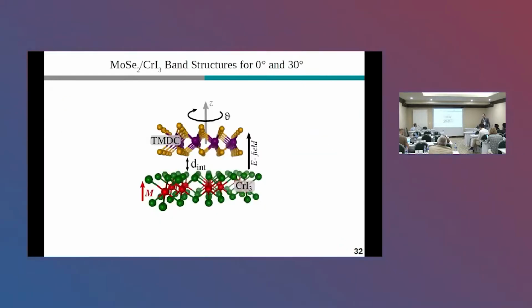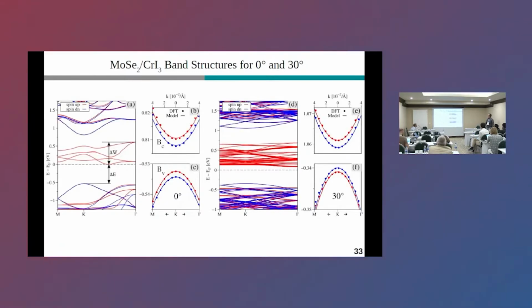And this is, of course, why we considered this in DFT and checked what the twist angle does, what a gate field does to this. And the story goes like this. If you start with a 0-degree twist angle structure, you can very nicely recognize the band edges of the TMDC here around the K valleys. These spin-polarized in-gap states result from the chromium triiodide, which is also responsible for the quenching of the PL peak for one light helicity. And this is a calculation without spin-orbit coupling to really resolve the proximity exchange alone.